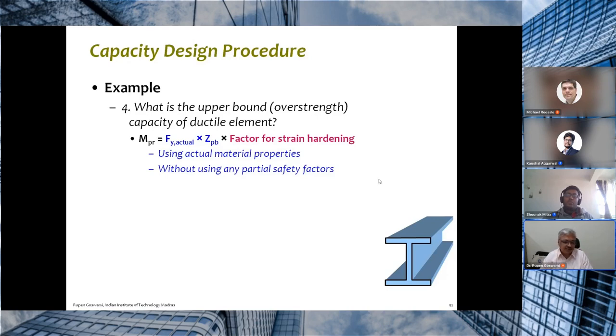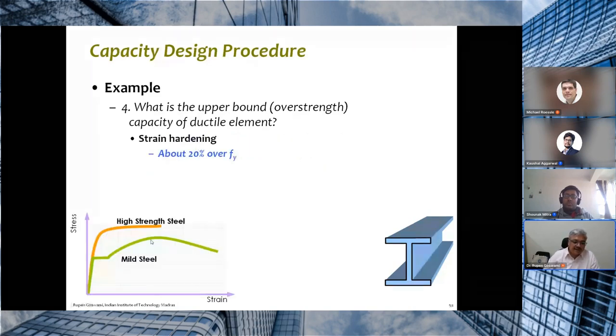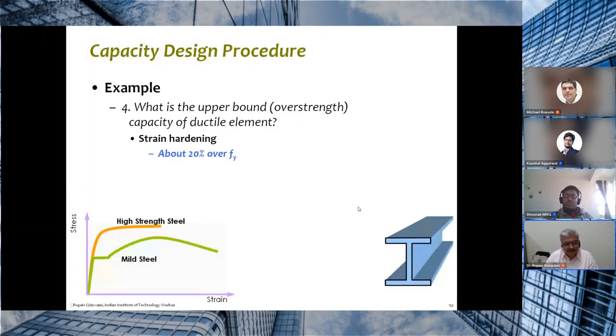two important parameters that come into the picture. One is that the actual material property need not be the same as what we used in the design calculation, in the sense that the actual strength provided can be more. Also, in design calculation, we have used a partial safety factor of gamma m0 and kept the stress level less than Fy. But when we calculate this particular Zpb, in reality there can be strain hardening of the material and even higher stress levels can be generated. Typically, how much more? If all other things are done correctly, including connection design, then about 10 to 15%, to something like 20%, over and above Fy is possible.